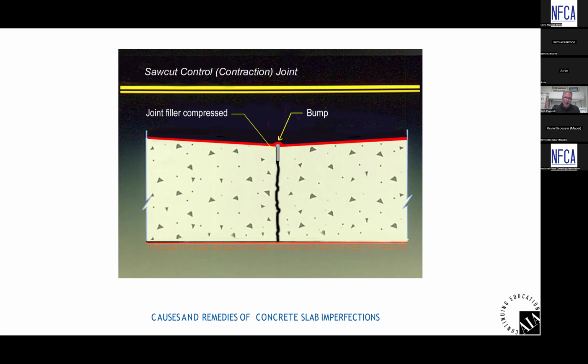If any of you are flooring contractors on the call here, by grinding that joint, patching it, and installing floor covering, you have done nothing wrong. You have done what you were contracted to do, to give a flooring installation that's flat, smooth, and aesthetically pleasing. The problem is a concrete issue. So after you do your installation and we're seeing something at that joint, the concrete has moved, and most likely it's slab curl relaxation, as you see in the pictures here.